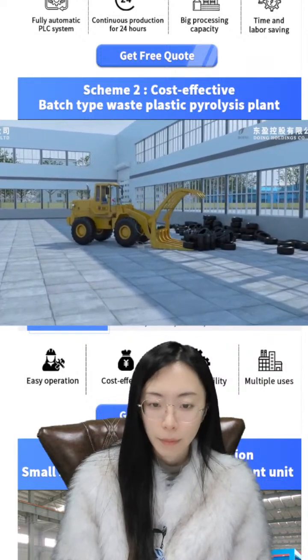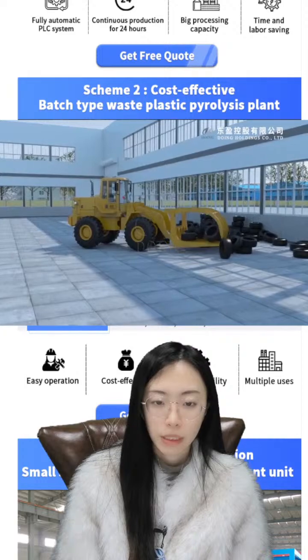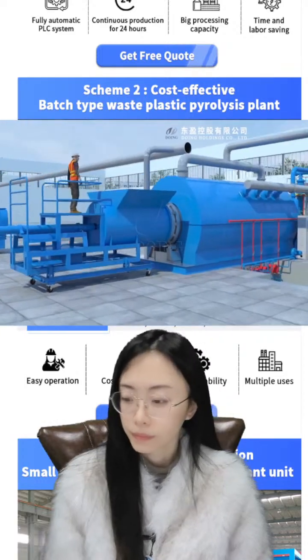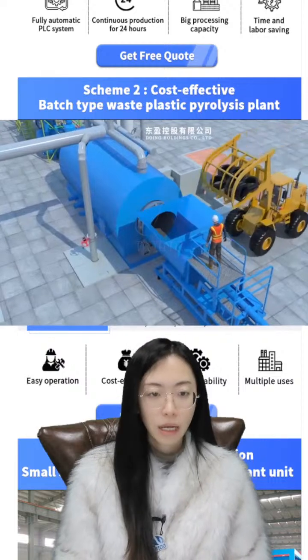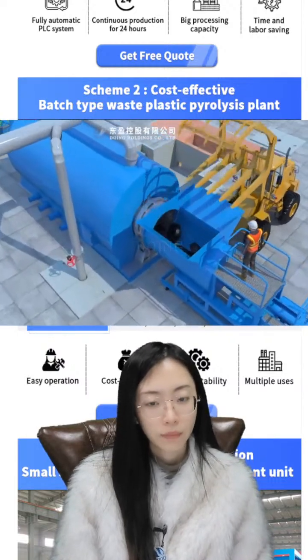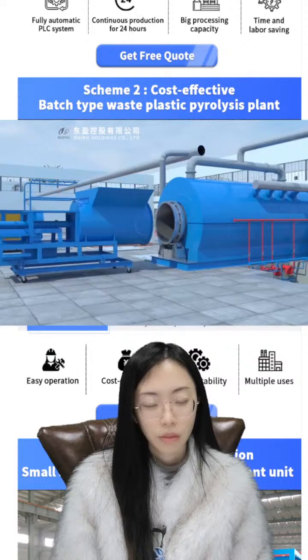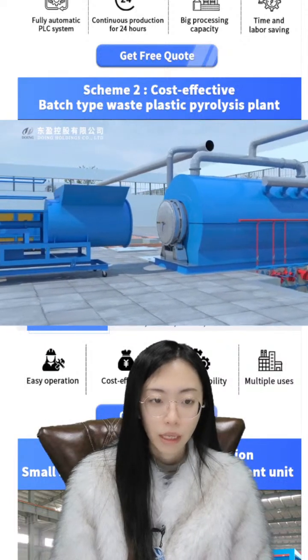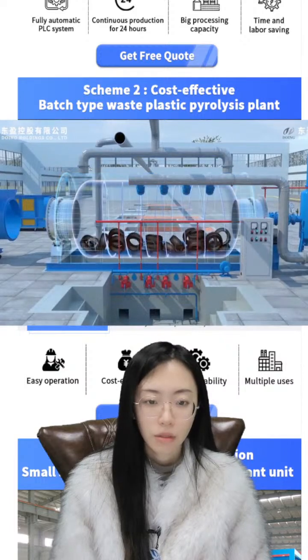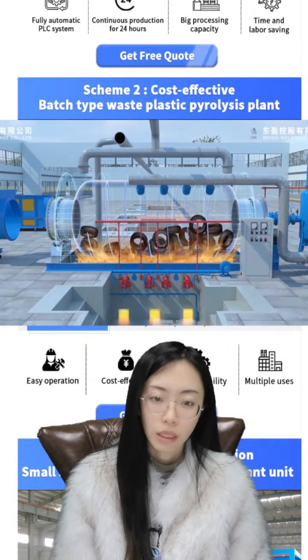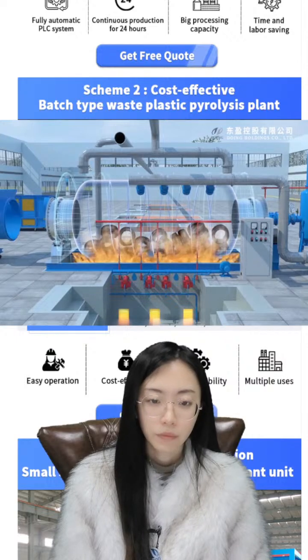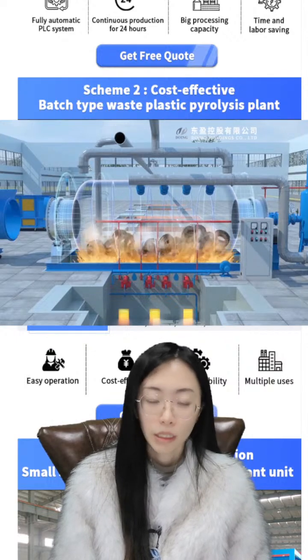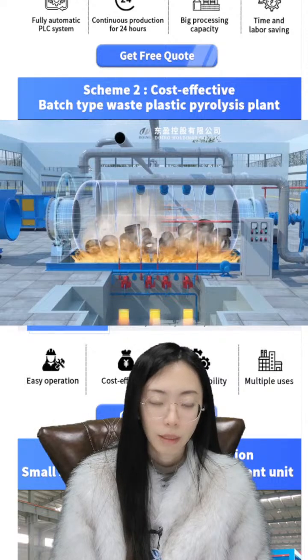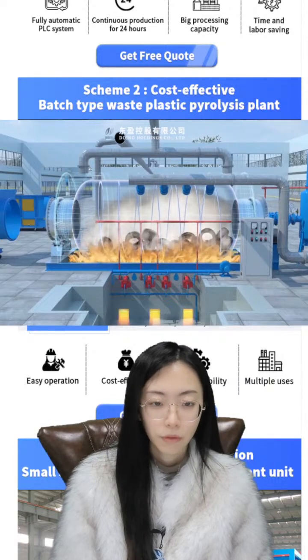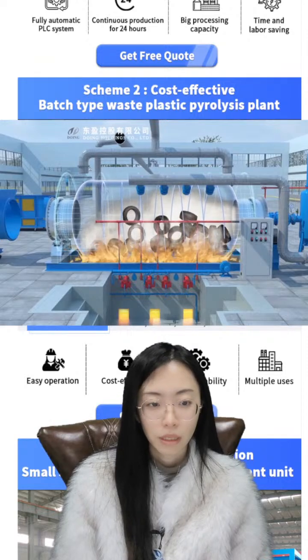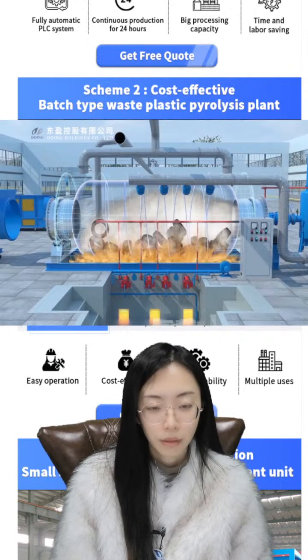This is the feeding step. This example is for the waste tire. We can also process household waste, woven bags, plastic bottles, or some tubes or plastic, except PET and PVC, which are not suitable for the pyrolysis working step. All the other plastics can be used, like PP, PE, PS, ABS. If we get pure plastic, the oil yield can be nearly 90%.